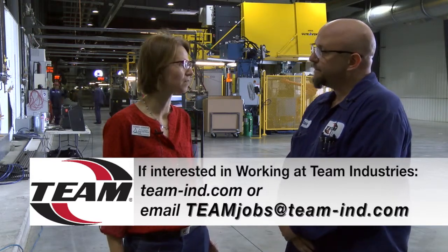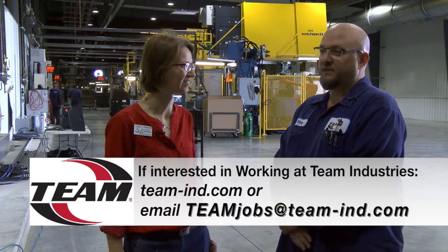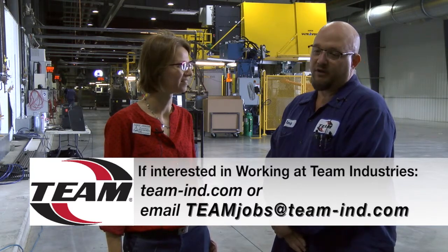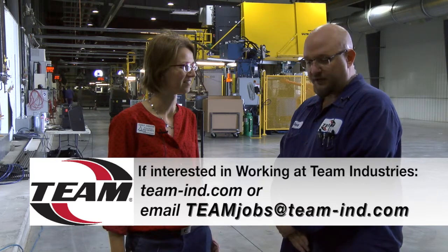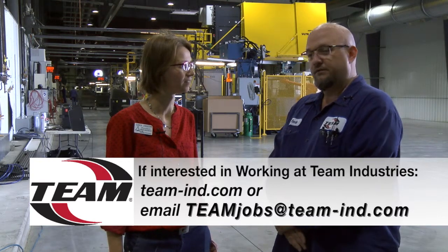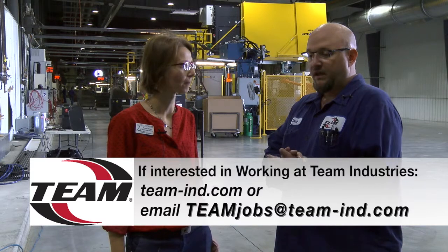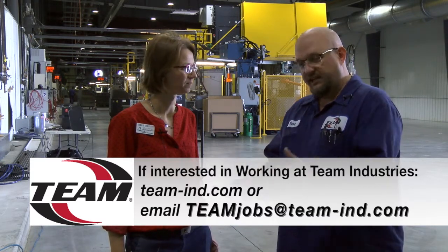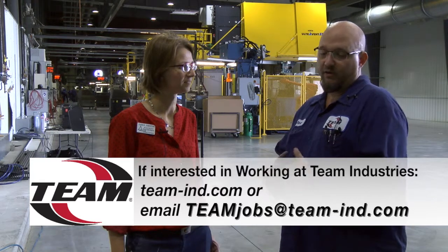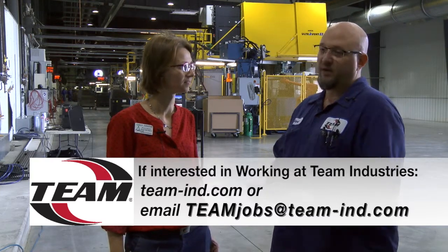Okay, so we just saw things being sprayed, things being poured. Describe the process a little bit about what we just saw. Well, we transport molten aluminum to the die-cast machine. At that point, it's sitting in a holding furnace. We will take it from that holding furnace and pass it down a chute into a shot tube, where we'll then advance it into the tool with a shot ram. So basically, we're getting a die ready by putting a die lubricant on it to make sure that the aluminum will not stick to the die. Sure. Injecting it with aluminum, opening the tool, ejecting a casting. We have a robot extractor which will take that casting and present it to an operator. That operator will then trim off any excess things that we use to make the part that are not sold to our customer. We put them in a container and ship them out.